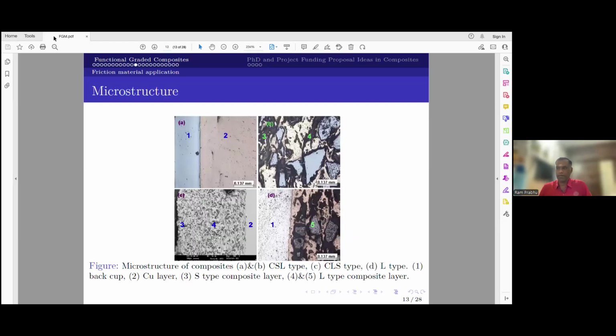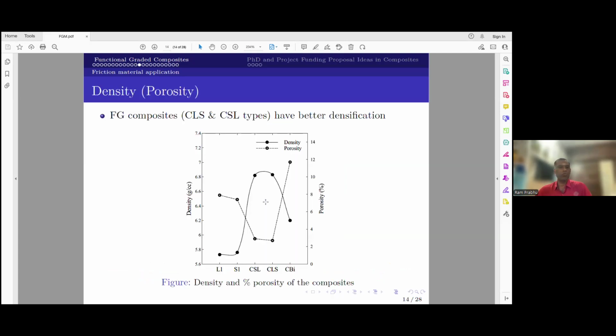So this is just to prove that you have a copper layer. This is a steel backplate, copper layer, then small size particle region, large size particle region in a simple optical microscope. And our job is to look at the interface: how is the interface, whether it is intact or any cracking is there. Now I want to see all these 4 layers in a single image, so I use a SEM: copper layer, large size particle, small size particle. This is the conventional composite, only a composite and a backplate without any copper layer, just to show that yes, whatever I have done has come. Now next is the density, whether I have a densified structure or not.